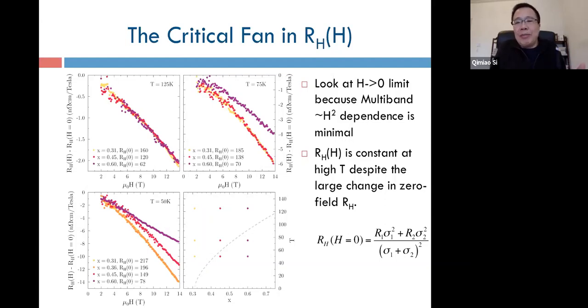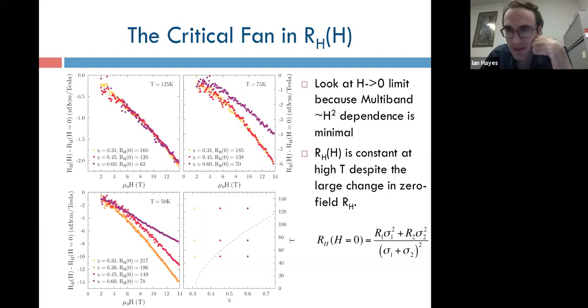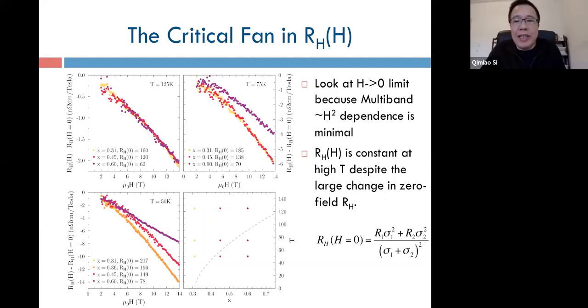And so in chromium systems, the answer is no, there's not a huge change, and in any case, there's not a lot of sharpening. In some of the heavy fermion quantum critical systems, the answer is yes, there's a very sharp change, a very strong, very sharp crossover feature, and that crossover feature sharpens as the temperature is lowered. And so you have this extensive, impressive collection of data in this system. I was wondering whether something along that line could be looked at.